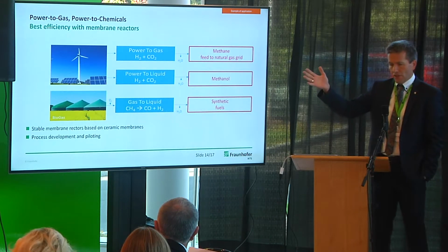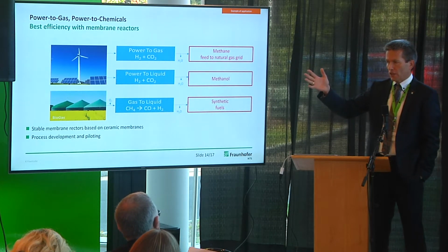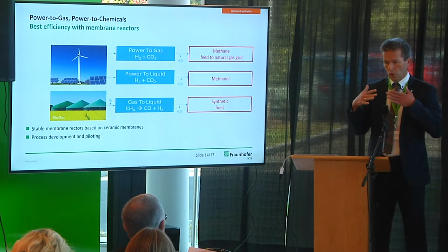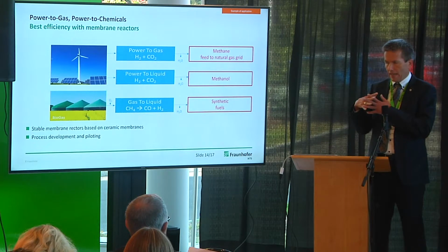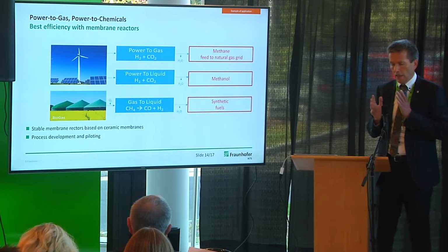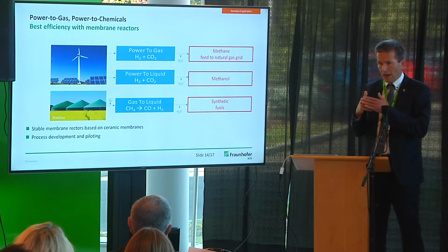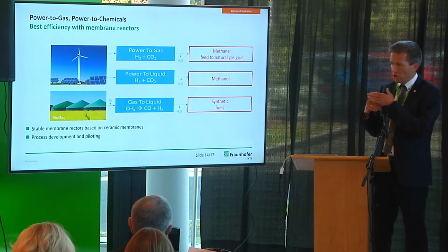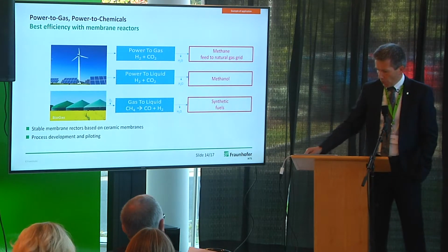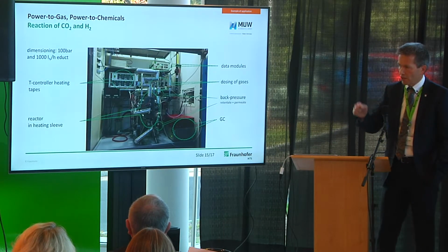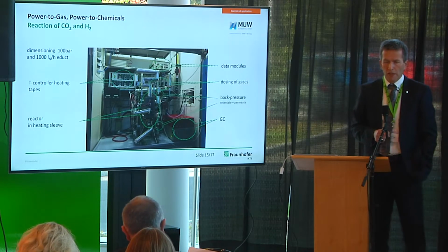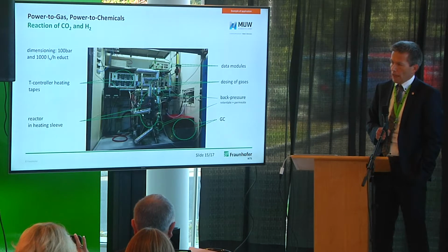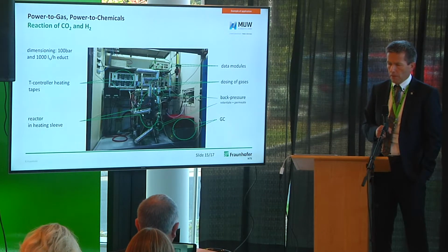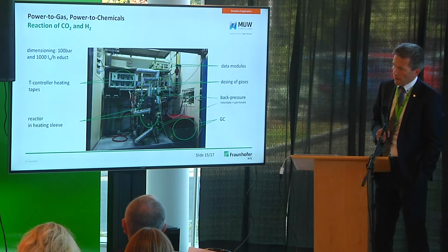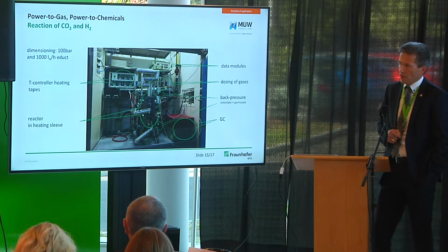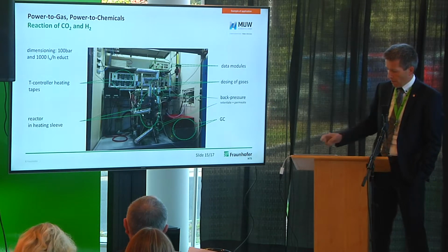and you can feed it to the natural gas grid. So it's very challenging and difficult because it's difficult to bring the kinetics and thermodynamics of separation and reaction on the same level, so that you can really combine it, so that you can prepare the catalyst coating directly on the membrane. But we are working on that, and here you see an example of such a reactor. So we have also people in our lab experienced in catalysis, in process engineering, and you see here this is a reactor for the CO2 hydrogen reaction to methane or methanol.